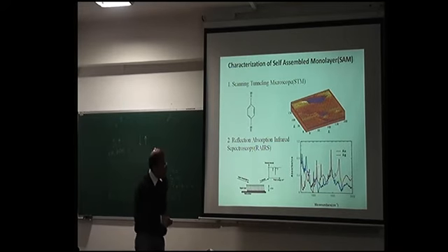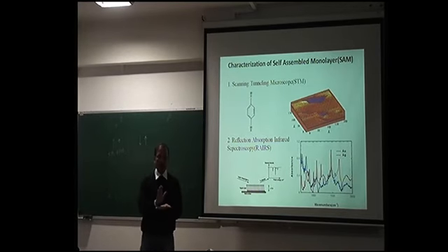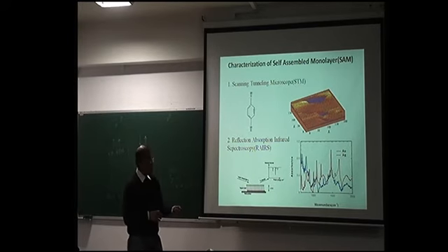So here I want to show you one thing: this molecule, you make a monolayer on gold and silver. Now it is theoretically predicted, and it is also experimentally true, that on gold this molecule stands like a vertical particle, okay? But on silver, it lies horizontal. So obviously certain vibrational modes will be absent on silver because your degrees of freedom are less in silver than in gold, and you can make that out by comparing the IR spectra.